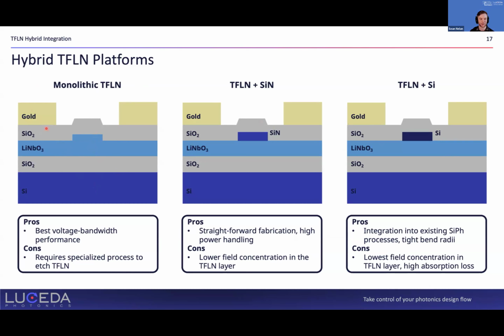By monolithically integrating your TFLN waveguides, you have all of your field or most of it in the TFLN material where you want it, and you can get the best performance. Now, it can be difficult to etch TFLN. So in a lot of cases, we integrate silicon nitride or silicon on top of that TFLN layer, such that we only have to etch the silicon nitride or silicon, which a lot of foundries are more set up to do. The downside of this is that you then have some of your optical field in the silicon nitride or silicon, which can be maybe lossy or at least pulls power out of the TFLN, which is the material doing the modulation. It has benefits, but it has downsides.